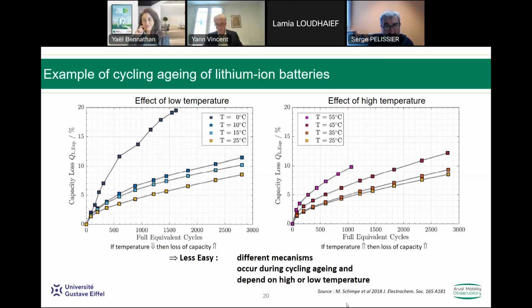If we are concerned by the cycling aging, it's less easy. On the left side, you see the effect at low temperature. For example, you start at 0 degrees and you have the higher capacity loss. And if you increase the temperature to 10, 15, 25, you decrease the capacity loss. But if you go further, on the right side, to 35, 45, 55, you, on the contrary, increase the capacity loss. So if you want to take care of the cycling aging, it's not so easy. You have to optimize, and there are two different mechanisms. So what does it mean for a car user or a fleet manager?